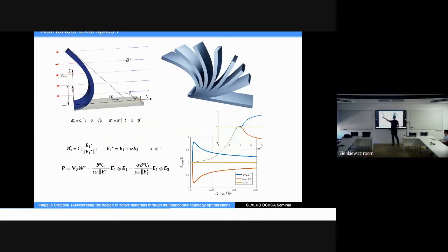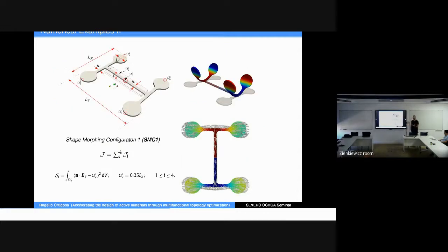So essentially, you have the material, B0R is this way, and then it's already magnetized, it's already saturated. You apply the magnetic field, and you see what's going to happen. The applied magnetic field is going to try to align B0R with BA. Let's take advantage of that and of the application of inverse techniques. And then what you can get is actually configurations like this one.